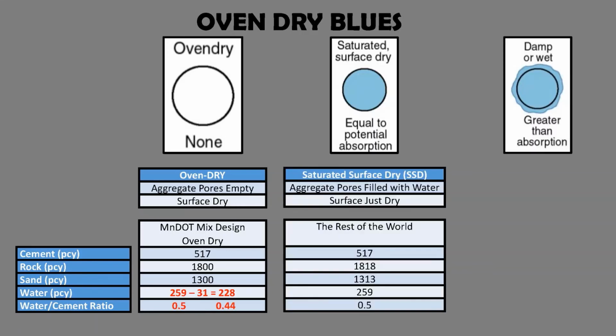Assuming our aggregate has an absorption of 1%, the rock would absorb 18 pounds of water and the sand would absorb 13 pounds of water in order for the aggregate to achieve saturated surface dry from the oven dry condition. This would result in our MnDOT mix design having a water cement ratio of 0.44. Now sit back, relax, and enjoy Pat Mancini's plea to Maria Maston, our MnDOT concrete engineer, to change oven dry to saturated surface dry.